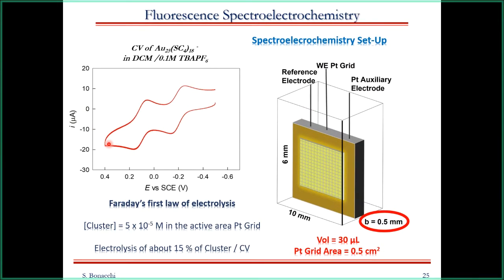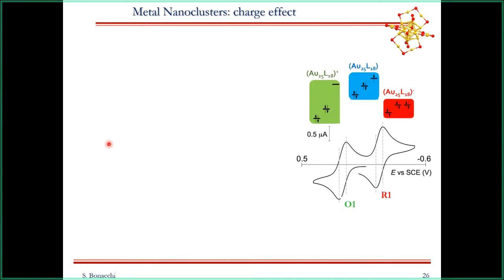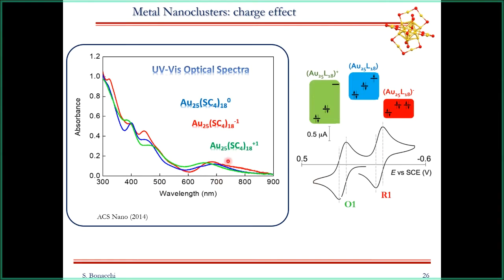And then we use this setup, first of all, to perform UV-visible optical spectroelectrochemistry analysis. As you can see here, even if these clusters have very broad absorption bands that basically cover the whole UV-visible range, starting from 800, 900 down to 300 nanometers, the optical spectra actually have different fingerprint features as a function of the charge of the cluster. You can see, for instance, this maximum that changes going from the neutral one to the -1 and the +1. So even if we have to have good eyes, as soon as you start to work with this kind of material, you can use the UV-visible optical spectra as a fingerprint to understand which kind of cluster you are working with.